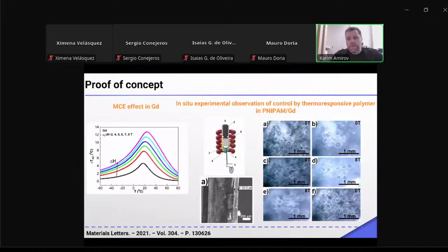Firstly, we were motivated by proof of concept, and we used gadolinium. Gadolinium is a simple classical magnetocaloric material which demonstrates a positive magnetocaloric effect. On the left figure, you can see its magnetocaloric effect measurements. As you see, its temperature changes by more than 10 Kelvin when 8 Tesla is applied. Why do we use 8 Tesla? It's just for proof of concept, and it's a usual laboratory superconducting magnet.